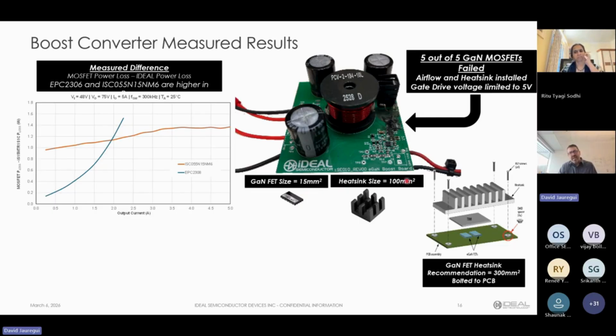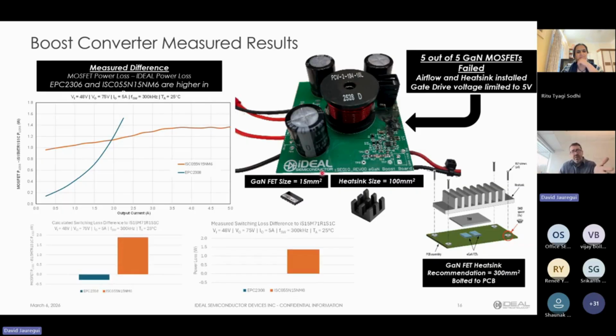I've heard rumors that GaN has a hard time working with hard switching applications, and that you really want to focus on soft switching applications, which is counterintuitive to me because with GaN, you want to leverage a low charge for that application. But nevertheless, there must have been something that we were doing wrong. We couldn't get it to the current, but if you look at the measured differential loss, this is what we predicted. The measured loss difference in the silicon device, Infineon, was about 1.5 watts versus 1 3/4.